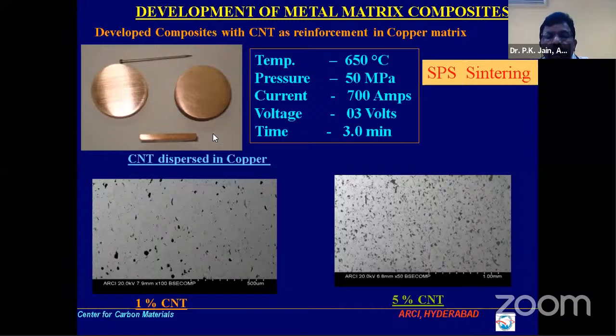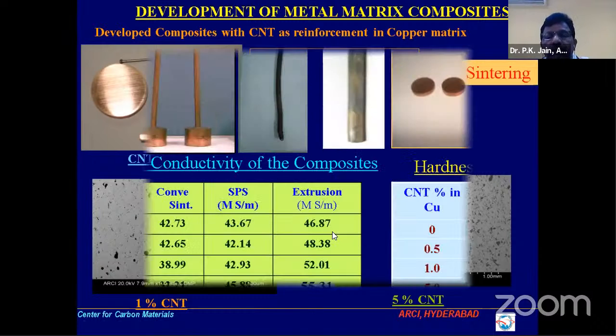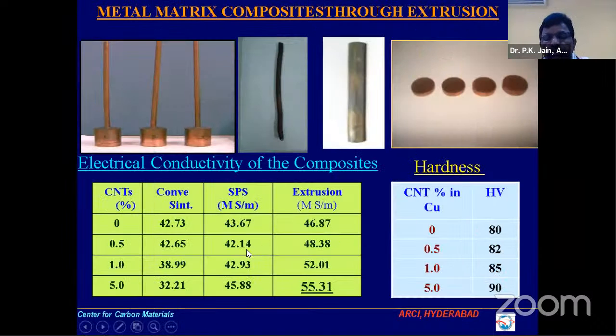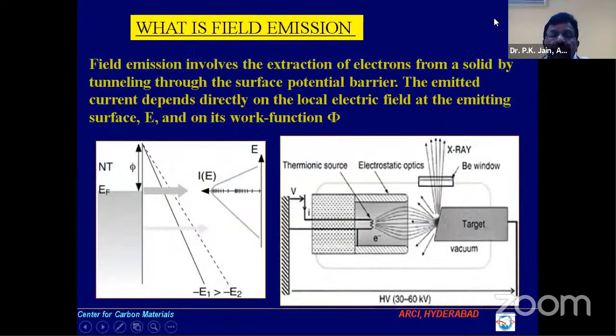A copper-based composite was also developed with the help of SPS, and then we found that the properties change. The electrical conductivity has increased by 55, and the hardness has gone up to 90. The field emission properties are also very important.